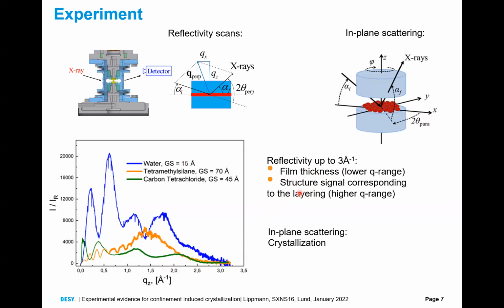This layering has a size of the short range order of the liquids. Therefore, it appears in the Q range where the structure factor of the liquids is. In the in-plane crystallization scattering, we focus mainly on searching for crystal peaks.